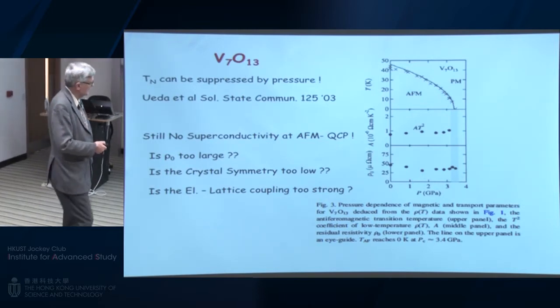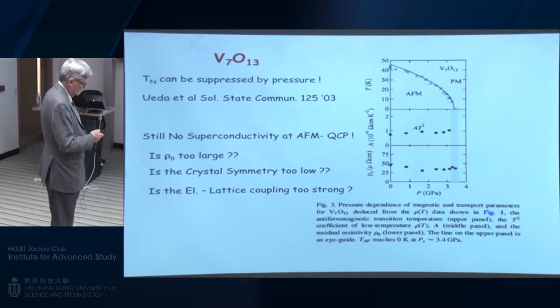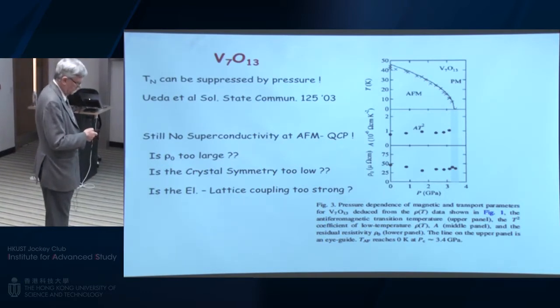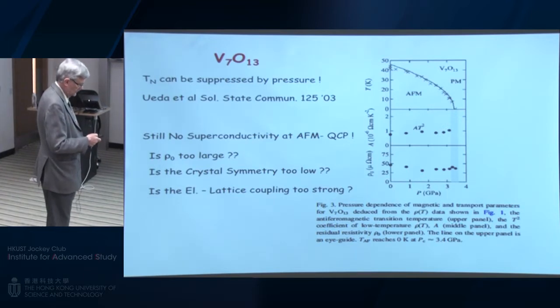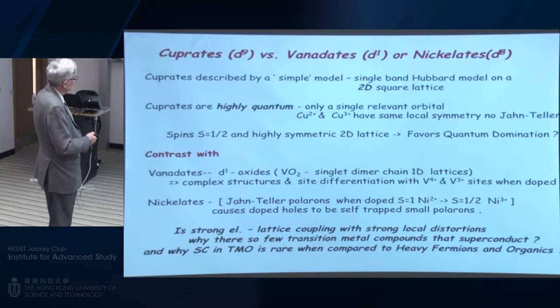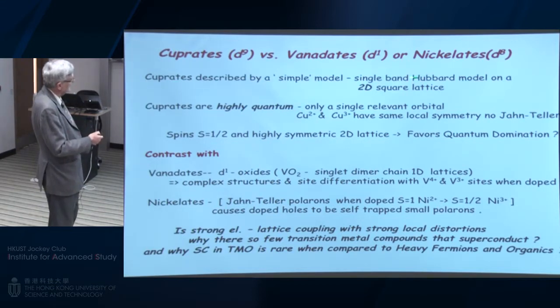And you might think you can simply go from 1 electron to 1 hole, and there would be a close comparison between the two. That's really just not the case. So if we look at the comparison between cuprates and vanadates, or also nickelates, we see cuprates are described by a simple model, a single band Hubbard model on a 2D square lattice. They're highly quantum because 2+ and 3+ have the same local symmetry. There is no Jahn-Teller effect, which lowers the symmetry when we have partially filled shells. It has spin a half, a highly symmetric lattice.